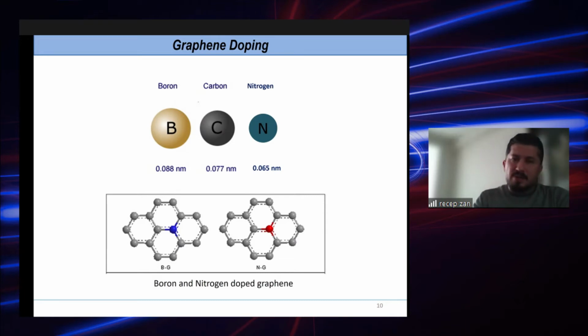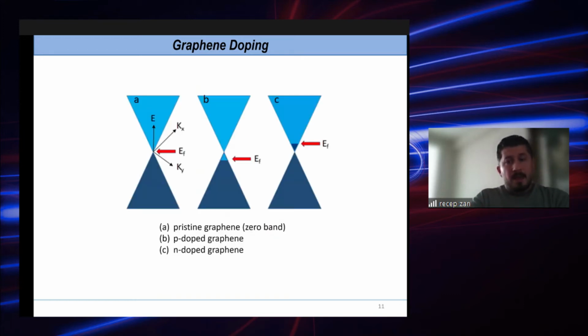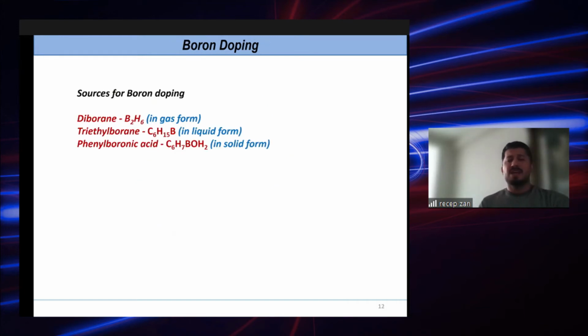But let me go back to why boron or nitrogen is used in the doping process: their atomic radius is close to carbon's, and the idea of doping is substitutional doping in the carbon structure. Rather than using other types of metals to do doping, we want to make sure that the graphene is stably and substitutionally doped using boron or nitrogen. Of course, we know the Fermi energy at the Dirac point in pristine graphene, and by doping with boron and nitrogen, we try to move the Fermi energy. In our case, when we dope the graphene with boron, we use 3 different sources: diborane, triethylborane, and phenylboronic acid.